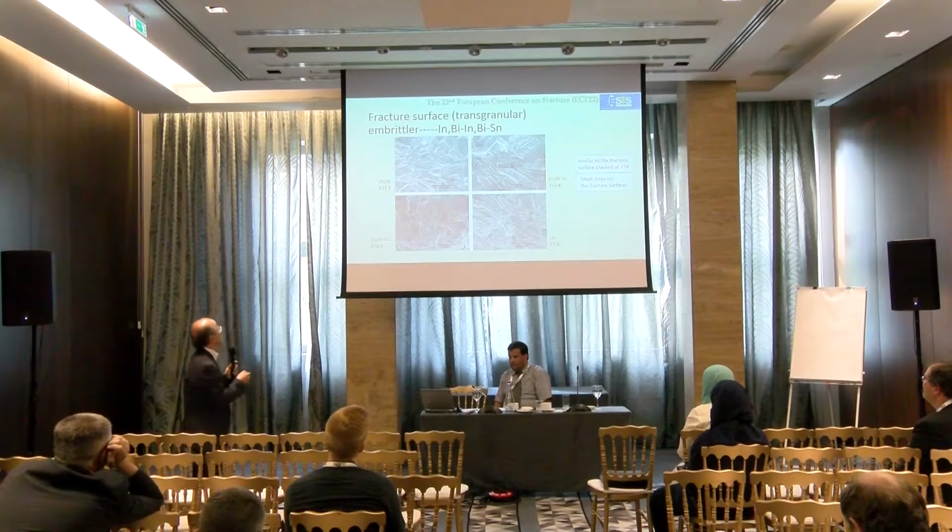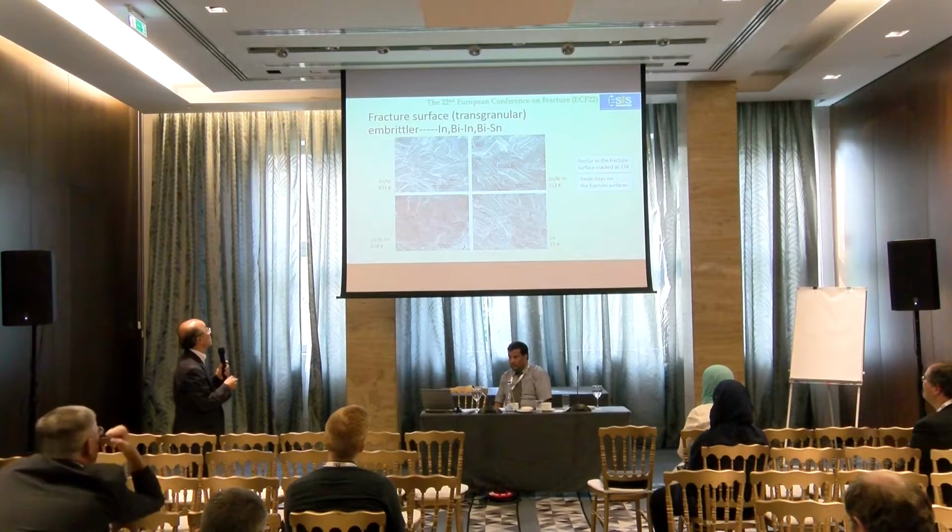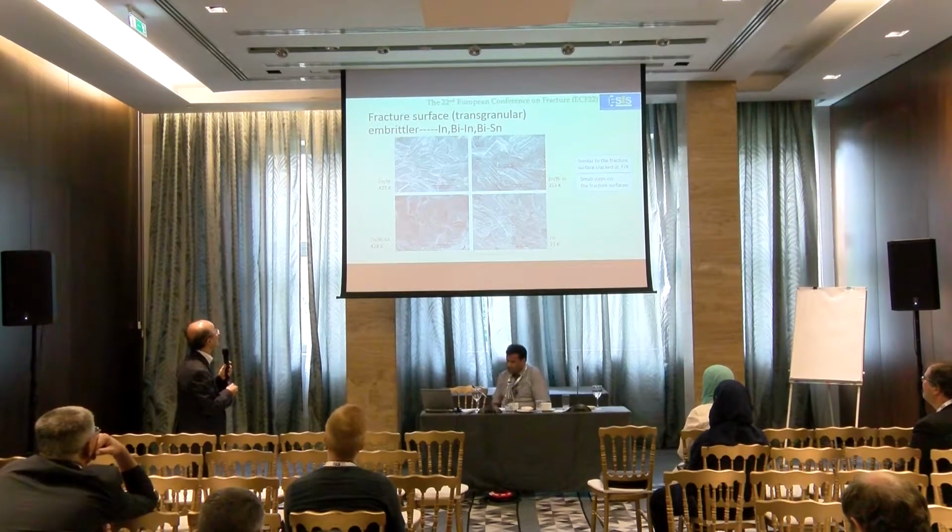However, in the case of liquid indium, bismuth-indium, or bismuth-tin, the fracture surface is completely different. The transgranular fracture surface is observed.